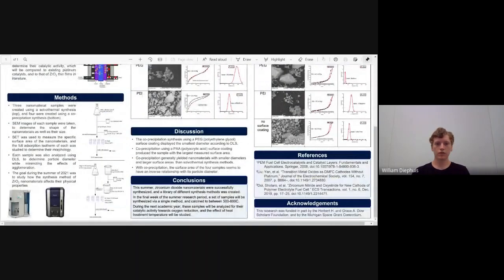Our methods for the past summer were as follows. We synthesized 7 different variations of nanoparticles of zirconium dioxide, 3 using a solvothermal method in an organic solvent shown in the top flowchart, and 4 using a coprecipitation method in an aqueous solution shown in the bottom flowchart.